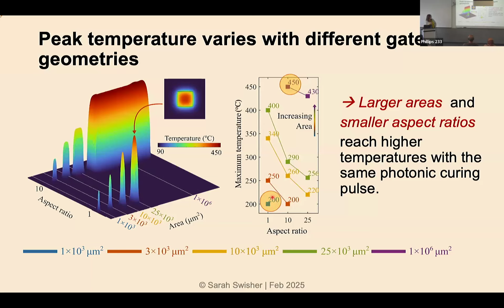And so it's really hard to measure the temperature on this time scale and as a function of depth. So instead of measuring the temperature, we know that the material conversion and the behavior of the TFT are very well correlated to that processing temperature. So we use the material conversion and the TFT performance to validate the model. So we say we know what 500-degree IGZO looks like in terms of its metal oxide composition. And so we can look at that and use that to help validate our model.